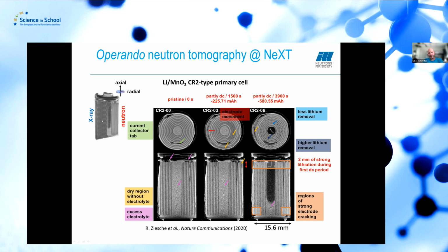Here now with a combination of X-ray and neutron, because here in the X-rays we see very well the nickel mesh that supports the anode, the cathode material, and again here the lithium metal that gets dissolved, and the electrolyte gets consumed here, and we see then the swelling of the cathode material, and that gives then rise to cracking in the electrodes. So these here were experiments that have been done at HZB. I just show you, but it gives you a rough idea what you can do on the scale of some 20 minutes, 1 hour scan time, half an hour, let's say.